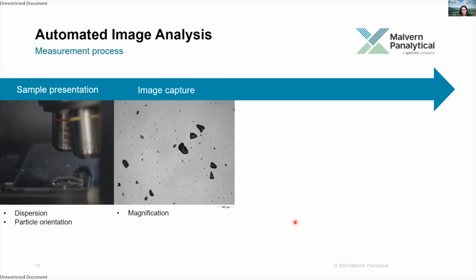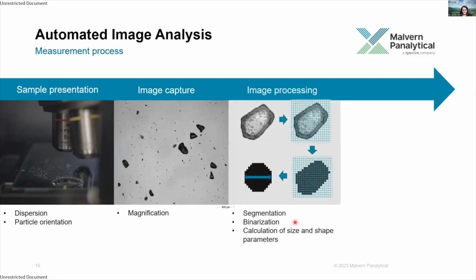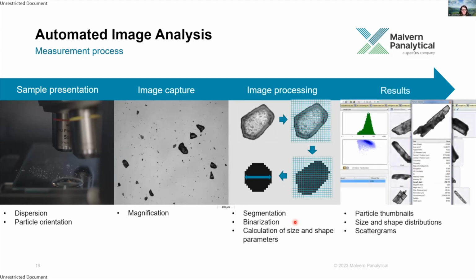Next, the sample is automatically scanned, and segmentation algorithms are used to separate images of the particles from the background. These images are then processed, where a vast array of size and shape parameters are calculated for every particle in the sample. And then finally, the results are reported for each particle, along with statistical results for the whole sample.